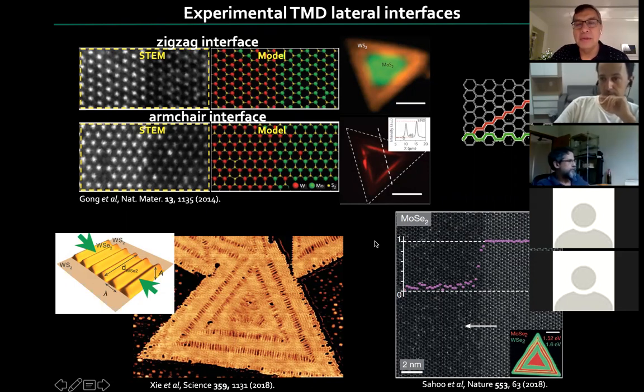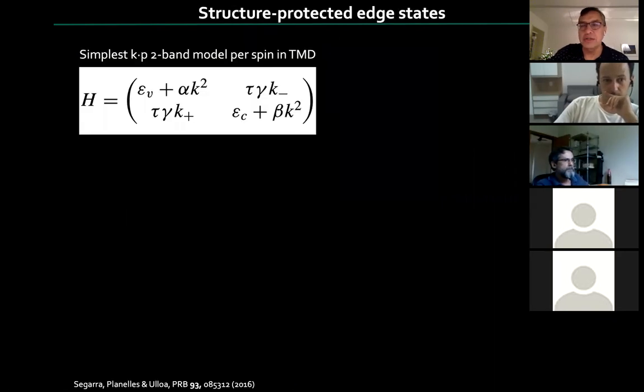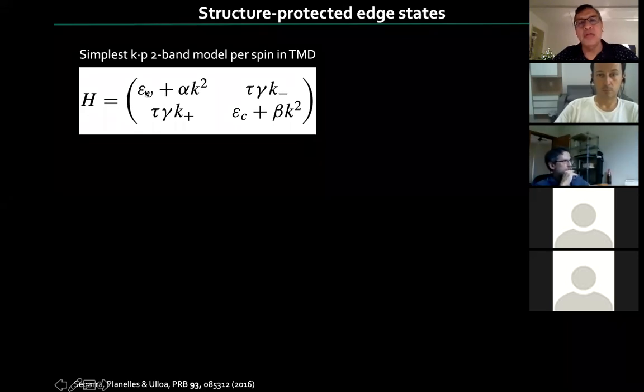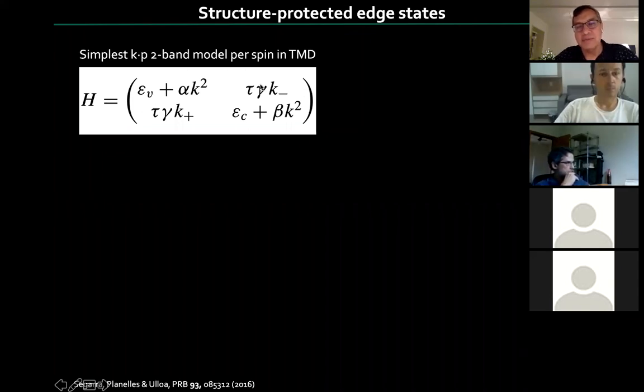Okay, so the question is what can you say theoretically about these states? For that, I have this, the simplest K dot P Hamiltonian, if you will. Because of the strong spin-orbit coupling, I can just consider one electron and one hole for each spin component. And so that will be this valence and conduction band energy. And this is the Hamiltonian that typically describes that. It is reminiscent of graphene by having these off-diagonal components. But of course, there is a finite gap. There is an asymmetry between the two orbitals in this case. And so it can be written like this.